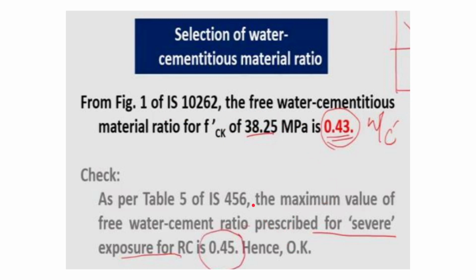based on the strength. So f ck prime value is 38.25, and from figure 1 of IS 10262 the free water cement ratio comes to be 0.43. This value has to be checked with table 5 requirements of IS 456, which suggests a maximum value of free water cement ratio as 0.45 for severe exposure of RC, reinforced concrete. So our value is 0.43, which is less than the 0.45 maximum value, so it is okay.